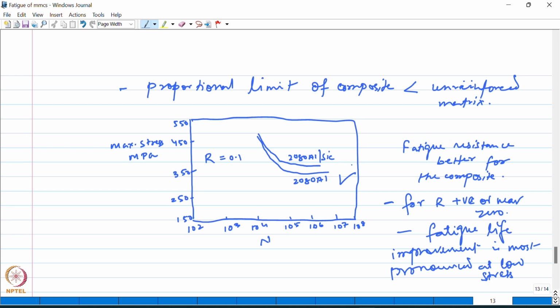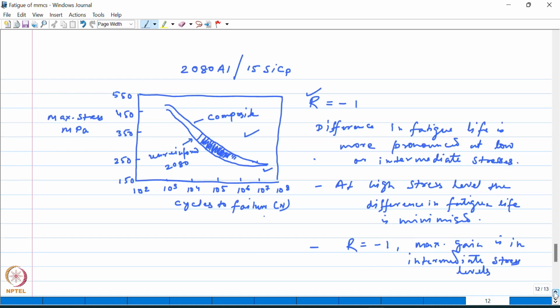Okay. So going back to this fully reversed condition, we can see that the plastic strain in the composite is higher due to theoretically lower proportional limit. Okay. And as a result of that, the deformation or damage resulting from the subsequent stress cycles is more in the composite, as I said. Okay. So that is why at fully reversed loading condition, we can see that even at lower stresses, due to the lower proportional limit of the composite, at least theoretically, plastic strain can be still higher, and therefore the improvement in the fatigue life over the unreinforced alloy is insignificant.